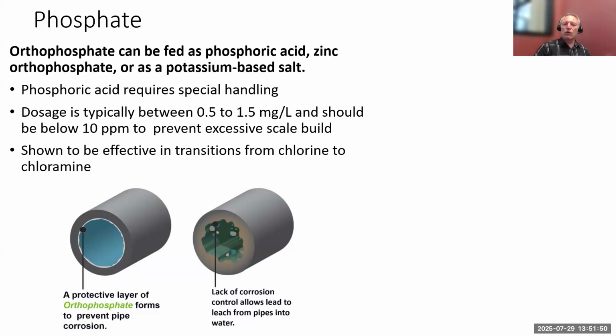And if you're feeding orthophosphate, that's been shown to be effective even in transitions from chlorine to chloramine. So that would be something you'd want to consider if you need to change to chloramines in the distribution system. Also, it seems to work best between pH of about 7.3 and 7.8. All of these major changes in things like pH and disinfection type and so forth can also affect other compliance objectives. For example, having a high pH might be great for orthophosphate. It's not going to be quite as good for disinfection efficiency.